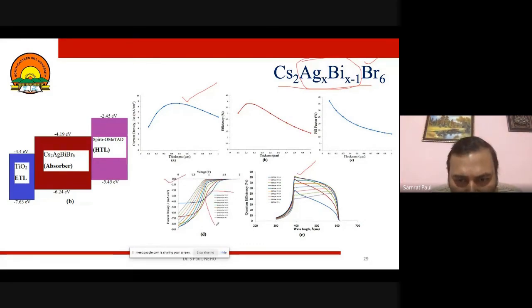I'm sorry it is not clear here, but with different ratios of Ag and Bi we have calculated, and we have found that if Ag is 0.8 and Bi is 0.2, this type of material gives the best results in a perovskite solar cell with an efficiency of 19%. So we could only reach 19% efficiency in terms of these double perovskites of this particular material.